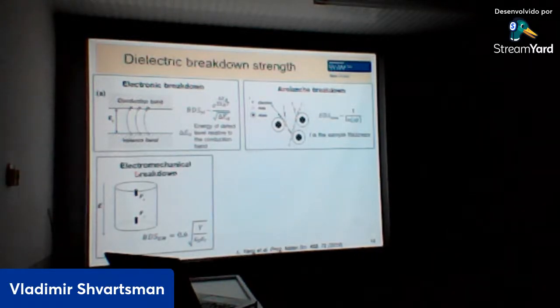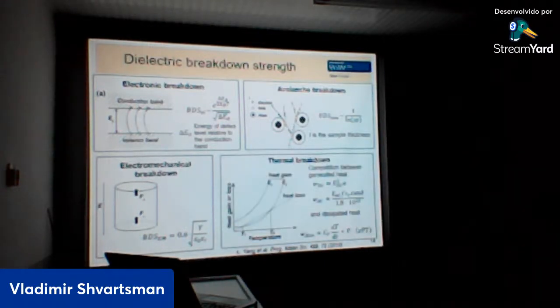So we can also have electromechanical breakdown, since when we have an electric field, we always have electrostriction, and sometimes in ferroelectrics we also have the piezoelectric effect. So we have a compression of our material under the action of the electric field, and this compression may result in mechanical stress, and this mechanical stress will also result in breakdown. And finally, we can have a thermal breakdown mechanism, since any current which flows through our material will induce heating due to the Joule heating effect. When the heat generated exceeds the dissipation, we will heat our material, the probability of transition of electrons to the conduction band will increase, and breakdown will be easier. So these are the main mechanisms.